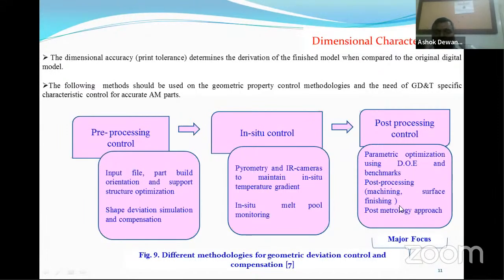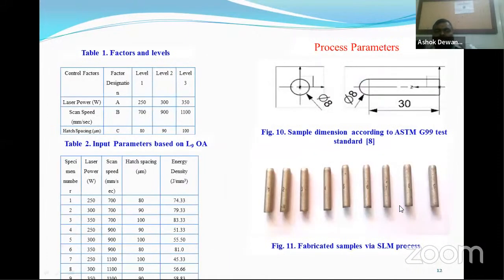So in this study, we have fabricated some wear specimens according to ASTM G99 on a 3D metal printer. And we have varied some of the process variables like laser power, scan speed, and hatch spacing. Laser power has been varied at 250 watt, 300 watt and 350 watt. Scan speed is 700 millimeter per second, 900 millimeter per second, 1100 millimeter per second. The hatch spacing is 80 micron, 90 micron and 100 micron.